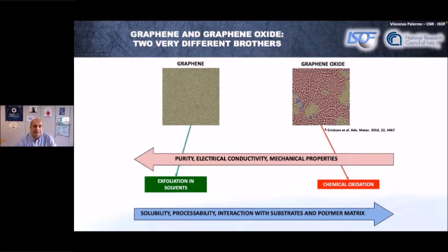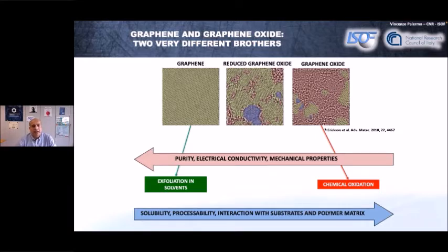The good thing with graphene is that you don't have to choose between one and the other, but you can really tune where to stop between graphene and graphene oxide. Or you can even directly produce graphene oxide that is partially oxidized, or even once you've gone to graphene oxide, you can go back and reduce it again. So you can take graphene, oxidize it, put it where you want, process it in water, and then reduce it back again to have something conductive that is not exactly graphene. You don't remove all the defects, but it's good enough for many applications, as we will see.